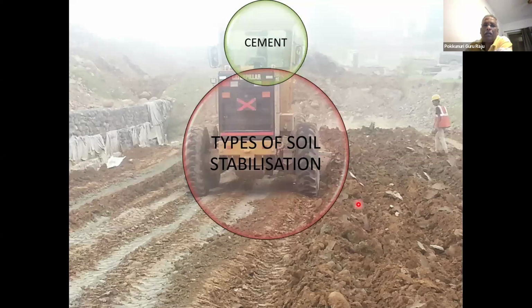But at any point of time, we have not used more than 3.5% cement to achieve the required CBR. CBR you anyway get by adding more than 1.5%. But generally, higher cement is required only when you are supposed to address the UCS values also being a requirement. Generally, it ranges between 1.25 to 1.5. It should be more than 1.25 to 1.5 for highways and expressways. So if it is to achieve that, you need to go close to 2.5% of cement stabilization. But the purpose of the stabilization is again the same thing. The method of stabilization we will be discussing in the different sections.